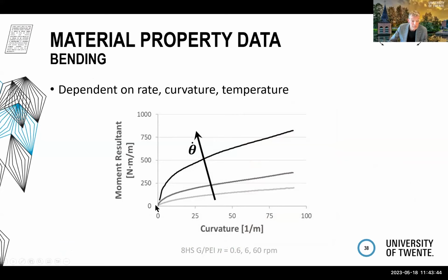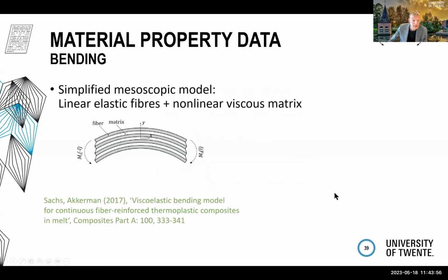So the bending moment increases with curvature, an elastic effect, and if we increase the rate, then obviously the stiffness, or the apparent stiffness, also increases. To understand what we're measuring, we did this sort of mesomechanical analogon with elastic fibers separated by a viscous matrix. And if you go through the equations, then you end up with this diffusion equation of the rotation angle. And well, that then apparently should describe the bending behavior of a structure like this. Well, okay, let's see how that works.